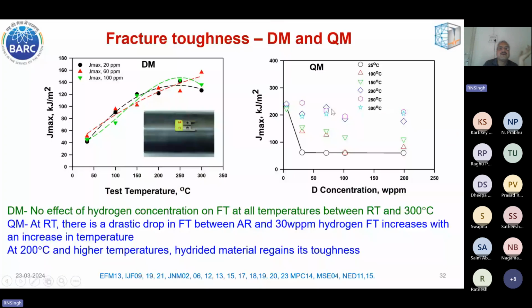Now, fracture toughness. Again, hydrogen is important over here. DM represents the double melted material, and QM represents the quadruple melted material. Initially pressure tubes were being manufactured from ingots produced by double melting, and you can see here that we have tested the material up to 100 ppm, and all the three curves are lying almost overlapping with each other. So no significant embrittlement effect is observed.